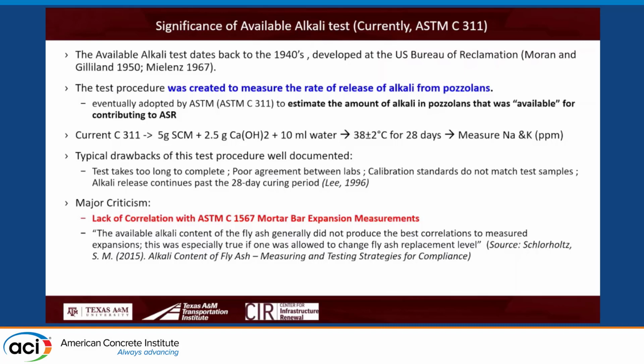There are 2 specific problems with this. One is that this test has a high coefficient of variation. There's poor agreement between different labs. There's also some research which says that the alkali release continues past 28 days. So the question is, why 28 days? But the major criticism of this test is that whatever it measures, there's no correlation with the ASR expansion measurements. Now that is a valid criticism, but the whole intention of this test was never to correlate with ASR. It was just to measure the amount of alkali coming out into the solution.